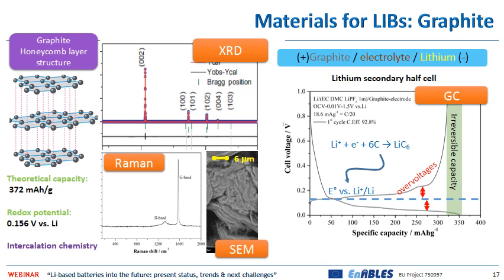Graphite, even in its very highly crystalline form in micrometric particles, can reversibly incorporate and release lithium ions, as shown in the voltage curve plot reported in this slide. In this voltage curve, we show the evolution of the cell voltage versus the specific capacity in a cell when current is flowing. As you can see, compared to the redox potential of the reaction lithium plus 6 carbon that gives LiC6, we have a smaller operating voltage in discharge and a larger operating voltage in charge. These two differences are related to the occurrence of overvoltages related to the motion of ions in the cell.